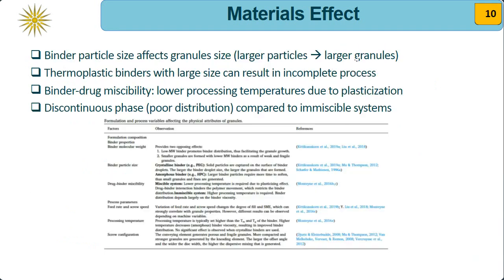The binder particle size also affects the granule size. For example, when we use larger particles of a binder grade, we produce larger granules. Thermoplastic binders with large size can result in an incomplete process. What is very important, and has been studied by other researchers, is the drug-binder miscibility, because when the drug and the binder are miscible, we can process the materials using lower temperatures due to the plasticization effect.